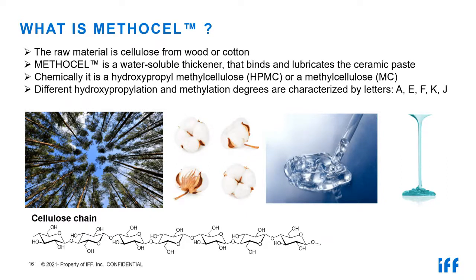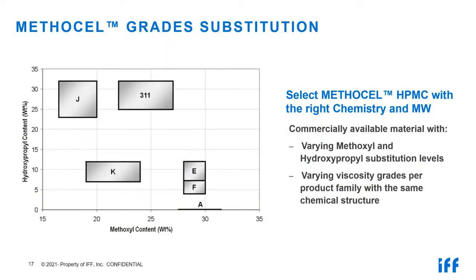Our METHOCEL is derived from nature. Our main raw material is wood, cellulose from wood or cotton. And after a very complex processing in a high pressure reactor, at the end we get a white powder, which is water soluble and binds and lubricates the ceramic paste. Chemically seen, it is an HPMC, hydroxypropyl methyl cellulose, or MC, which is a methyl cellulose. These are two different classes, and in order to characterize them a little bit easier, these classes received letters. So we have a METHOCEL A class, this is a pure methyl cellulose, and several HPMC classes, METHOCEL E, F, K, and J.